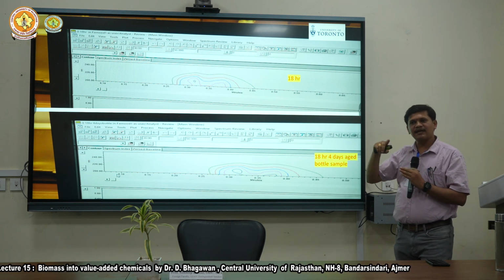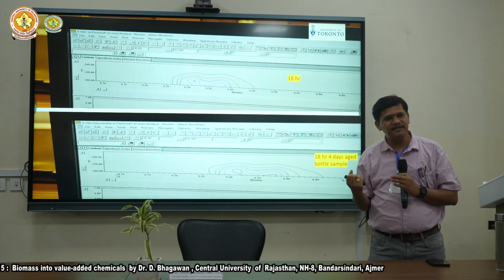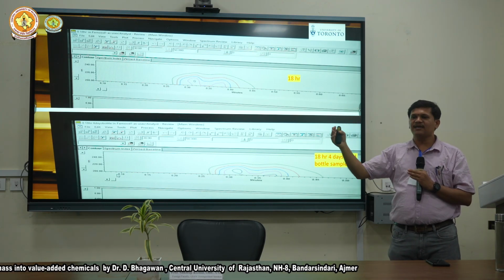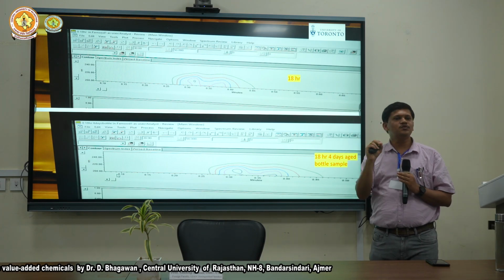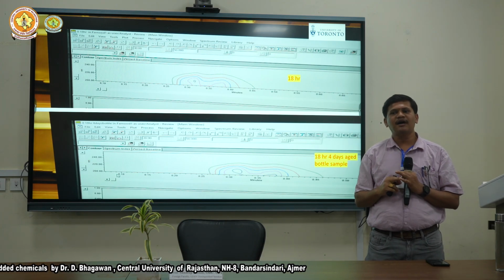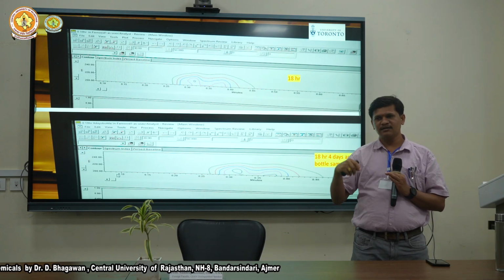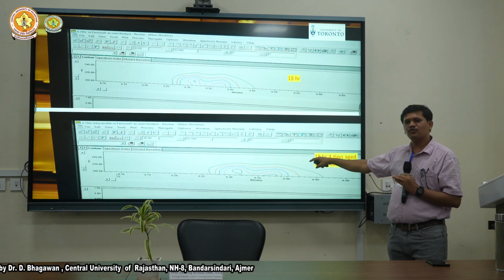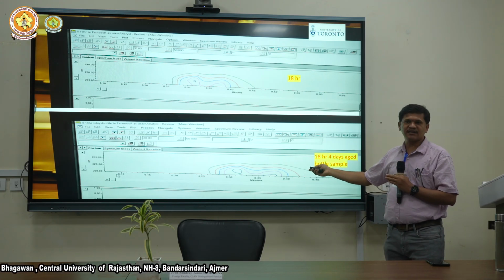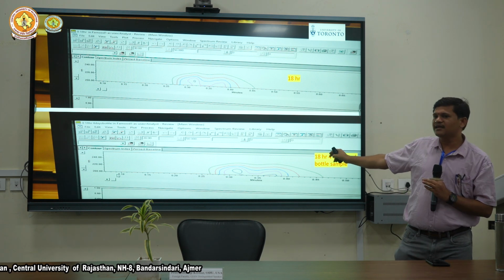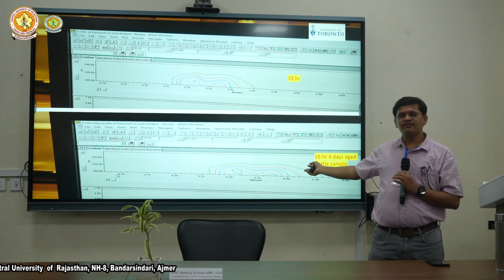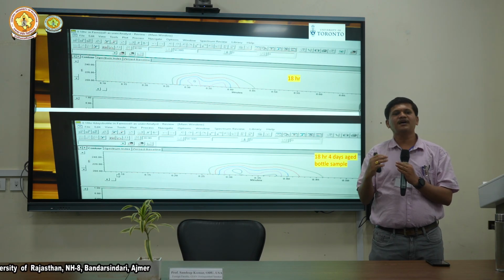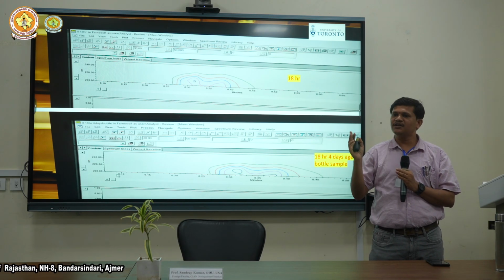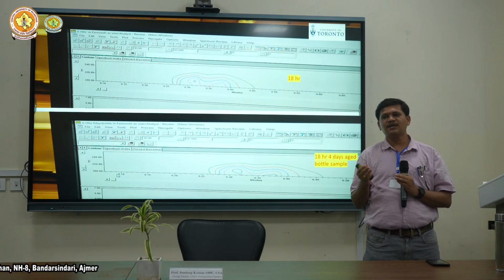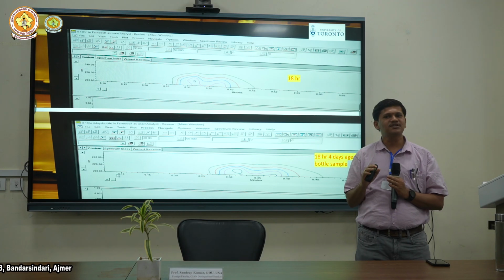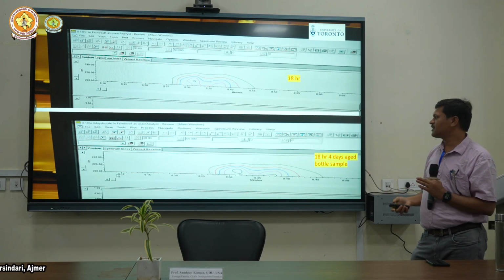This compound formation catalyst is still working without photo intensity. This catalyst has the capability to continue the reaction. So if you don't use photon energy, your catalyst still has the capability to continue the reaction and convert the component. The same thing happened here. The concentration of the new compound has still increased, and there is no backward reaction. If a backward reaction happens, then it is not suitable for industrialization. If you leave the solution for separation or some other purpose, the compound formation is going to continue, and recombination, oxidation or reduction of the compound is not going to take place. The original compound will be retained within your solution.